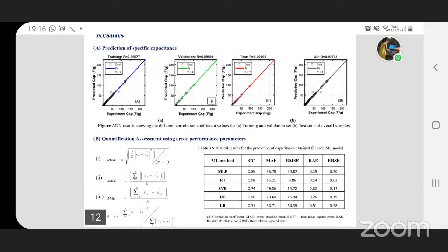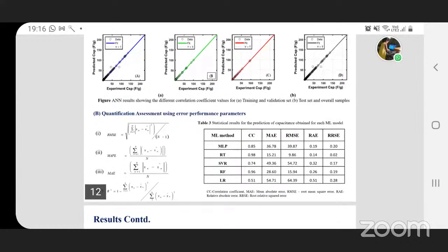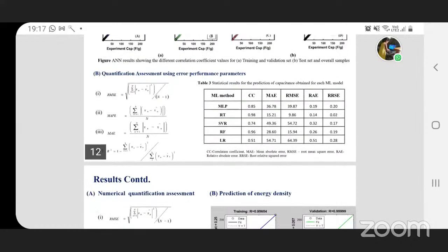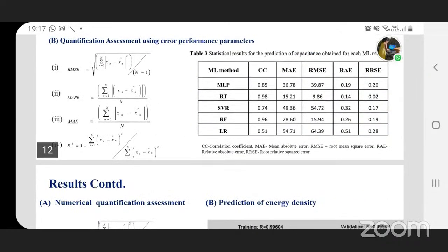So as far as the results are considered, we can see for all the different models that we have suggested, the training, validation, test, and overall samples for ANN were giving the correlation coefficient value as 0.99, which is approximated as 1. And we can see most of the data are quite fitting the expected as well as the predicted values. And for the quantification assessment, we have taken 5 different error performance parameters, and their values were calculated for different ML methods. That is, MLP was having a correlation coefficient value of 0.85 and so on.